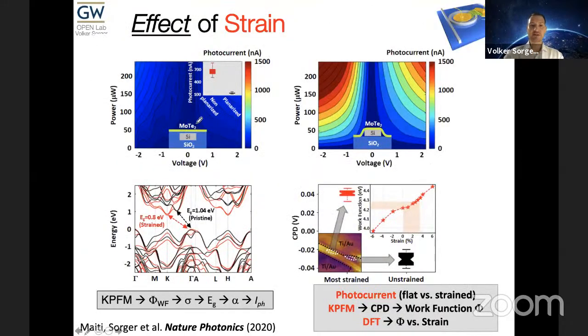Now we performed a control experiment. Basically, we have the same 2D material here that is flat. For this case, we do not observe any photocurrent as a function of voltage and optical power. Notice it's all blue. There's basically no photocurrent down here. Once we strain it, so we wrap it around, we have a pretty high photocurrent now. Notice this is experimental data, simply binned, as opposed to simulated data. Then we verified this strain effect by performing Kelvin probe force microscopy.